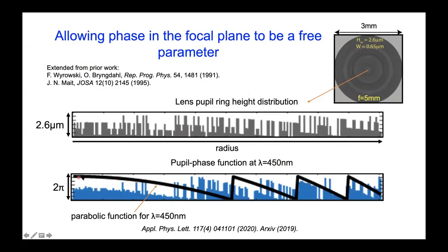And you can compare that to the parabolic phase function, which we are all taught in undergraduate or high school physics on what the lens should look like. And that's what that is. And you can clearly see they're quite different. And even more interestingly, this phase, of course, varies with the wavelength. So we can look at them at different wavelengths. I should point out that these lenses are fabricated using grayscale lithography using various tools, but primarily we work with laser pattern generation. And I should acknowledge quite a bit of support from Heidelberg Instruments for the same as well.